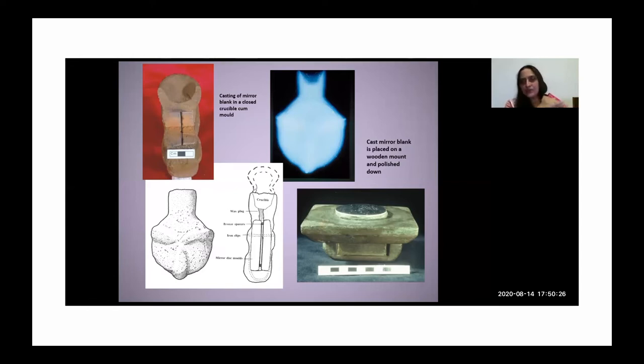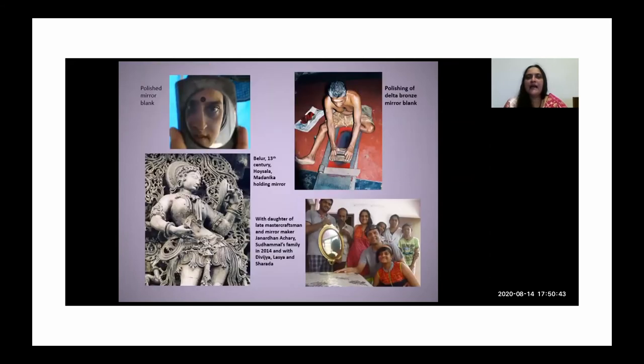And that stage is also quite important, because when it's embedded like that in resin and kept in this wooden polishing board, then the brittleness is minimized, and then it can be polished to get that very brilliant polish. So you can see it's a very silvery alloy which is put over there. And then we have the phases of polishing the mirror. So you can see there what it looks like after it's been polished.